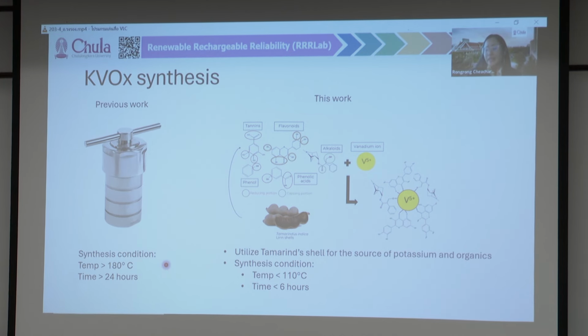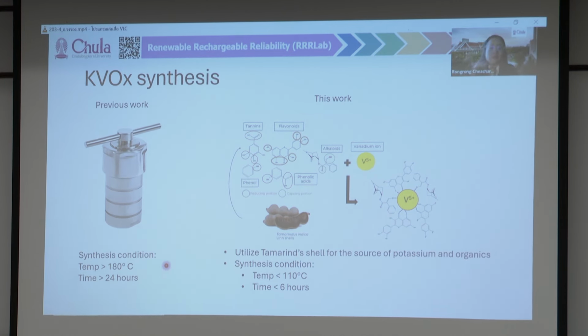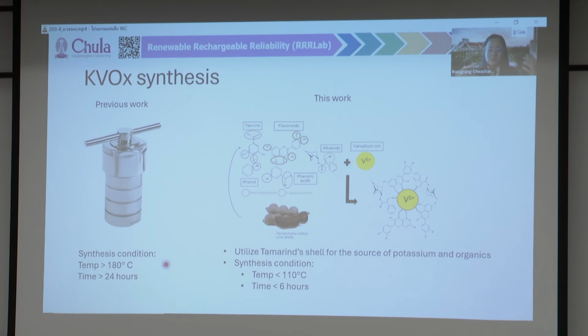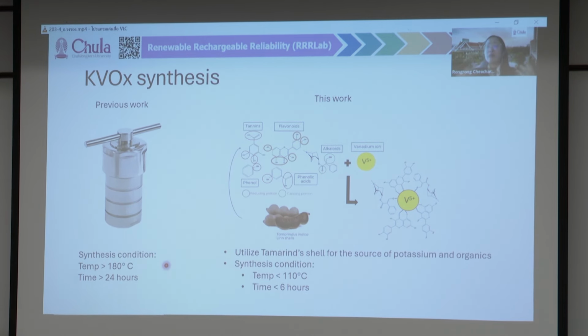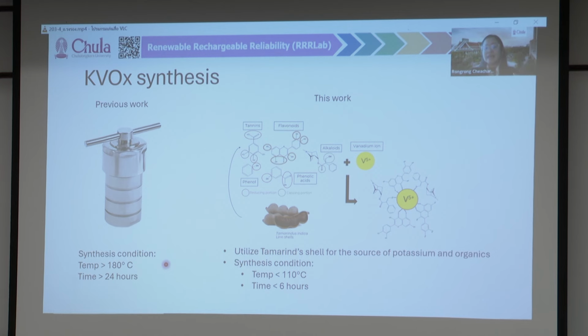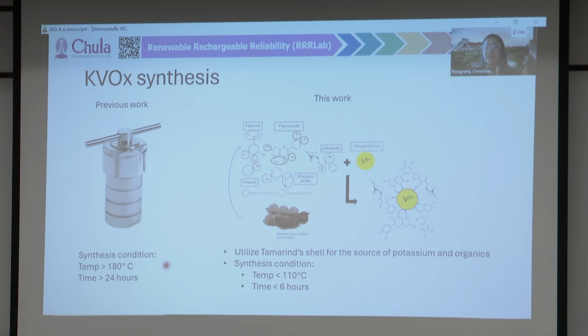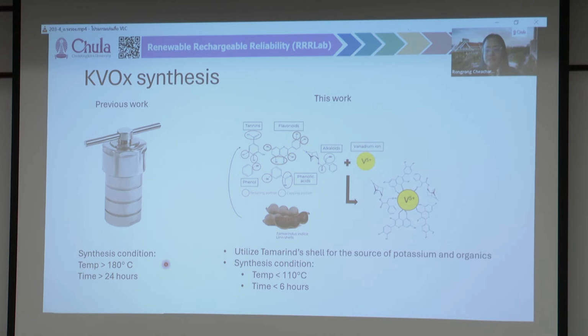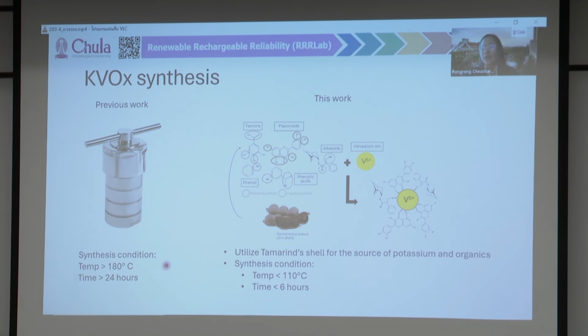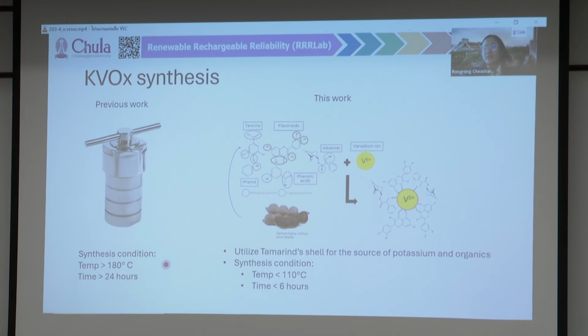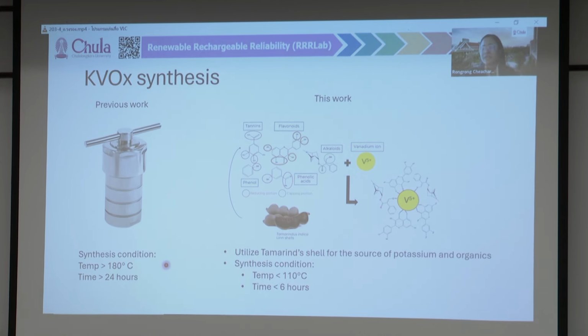So in this case, we propose to lower the amount of energy required to synthesize the potassium vanadate cathode by doing a green one-pot synthesis at a temperature below 110 degrees Celsius, with a reaction time below 6 hours.